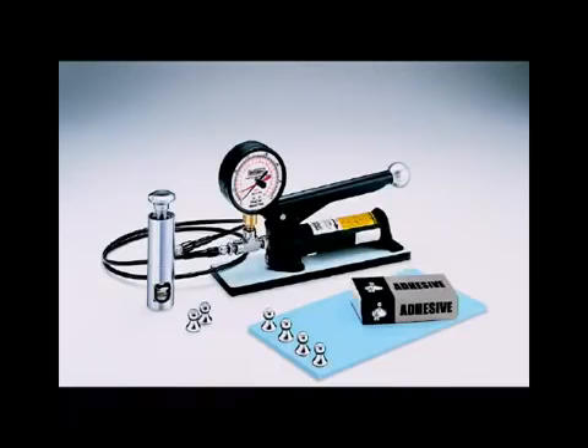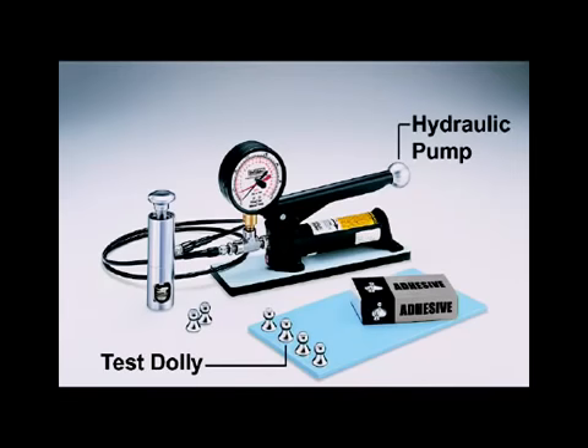The major components of a pull-off adhesion tester are a test dolly that is adhered to the coating, a pressure source such as a hydraulic pump, a pressure gauge with a drag pointer, and an actuator for physically separating the dolly and the coating from the substrate.